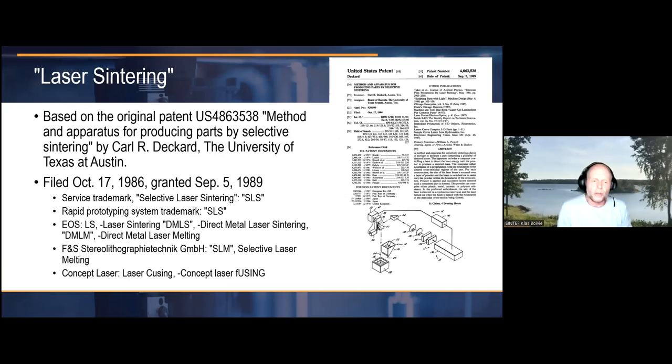The problem is that in powder metallurgy and ceramics, sintering is the term used when you are fusing powders which do not melt. But in this process with laser, they actually do melt. So it became very difficult because metallurgists wouldn't accept this name, because they said, you say it is sintering, but by definition it is not sintering. So they had to change the name for that.